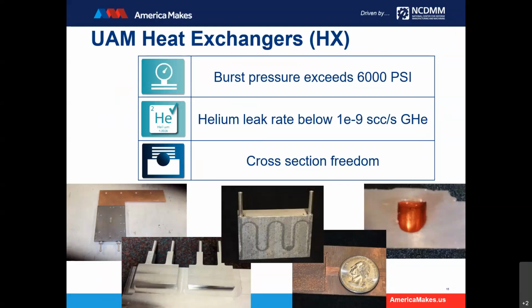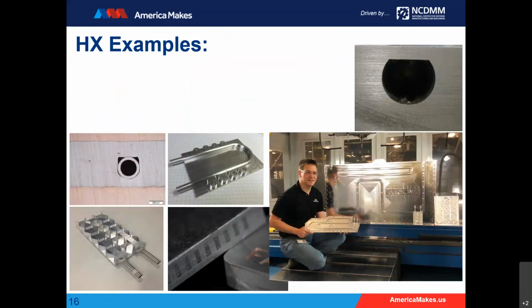As you get into larger and larger channels, we do need to use some support materials. So when we're welding over a large void, we are pressing down with a considerable force. If you don't have something in that cavity ready to push back, you can deform metal into the cavity. So larger structures like the picture shown here with Justin, we're going to use a water-soluble support material that is patent pending right now. But you can see, the applications range from something as small as 1 inch by 1 inch up to heat exchangers that are maybe 5 foot long. Everything along that scale range is possible.